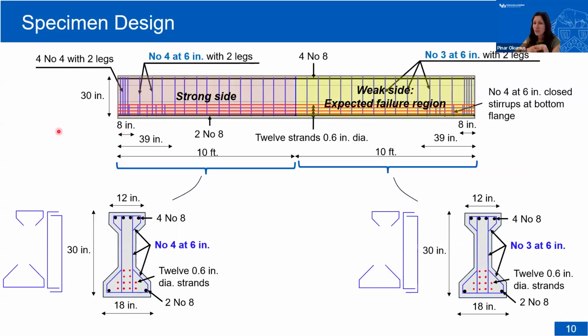This is our specimen design. We have one beam, but we're actually collecting 2 beams' worth of data out of it. So we have a weak side. Half the beam, the right-hand side, we call the weak side, is reinforced with number 3 stirrups at 6 inches. We expect the failure to happen here. On the left-hand side of the beam, we have number 4 bars at 6 inches. We call it the strong side. We know we're not going to be able to fail the beam on the strong side, so we won't be able to get the capacity, but that doesn't mean we cannot collect crack width versus applied load data. So that's what we're getting from the other side.